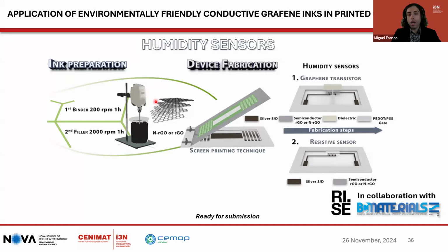Finally, humidity sensors were also built in collaboration with RISE in Sweden and BC Materials in Bilbao. And this is work ready for submission. In this case, a screen printed humidity sensor based on graphene was fabricated. Two structures were adopted. One as a resistive sensor, with the reduced graphene oxide acting as a sensing layer sandwiched between two silver electrodes, or as a graphene field effect transistor acting as a sensor.